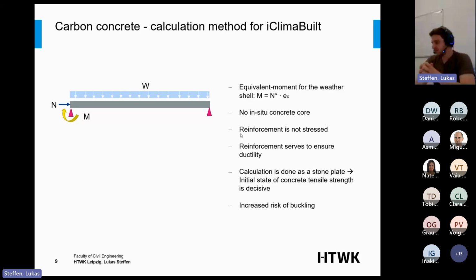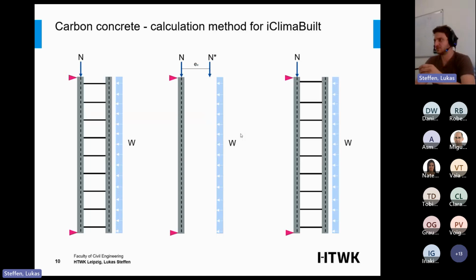One problem here is buckling, but we proved in the simulations that buckling is not a problem with the anchors and the weather shell, because we reduce the spacing between the anchors, and buckling can only happen between the anchors. For iClima it's fine, but it's not standardized. The calculation for the stone plate is standardized, but not buckling.